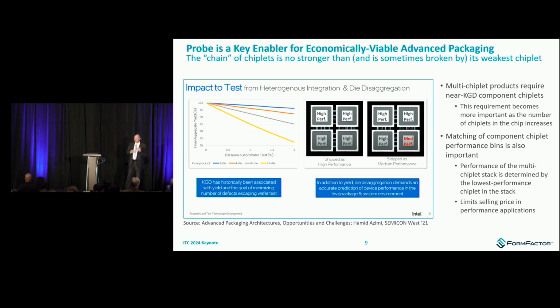And you can see from this, not surprisingly, even at a fixed gap to known good die, let's pick a percent, right? A percent of the die coming through wafer test actually make it through but are not good, because of gaps in test coverage, because of sampling problems, whatever. If 1% of your chiplets going into the assembly process are not going to work, for a single die, that's not a big deal. All you're doing is throwing out the cost of that die plus the cost to package it. But take the most extreme example on this chart, a 16 die stack, right? That has really profound implications.